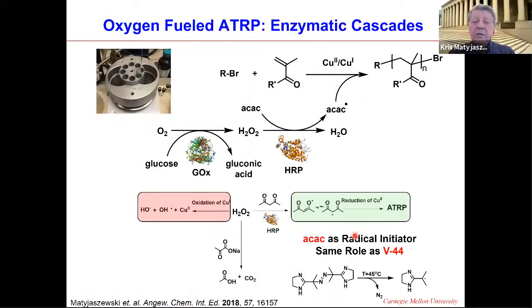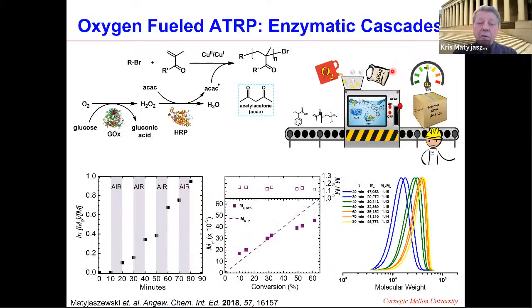Alan and Leah, they also look at the system which is really relying on oxygen. So it needs air to start polymerization. So this is an enzymatic cascade starting from this glucose oxidase process and hydrogen peroxide. But now we can eliminate this V44 radical initiator by using a second enzyme, horseradish peroxidase, which in the presence of acetylacetone produces ACAC radicals, which can reduce copper-2 to copper-1 in situ and start the reaction. So this has been really done for several different monomers. This enzymatic cascade, glucose oxidase, horseradish peroxidase, acetylacetone, and polymerization in situ.